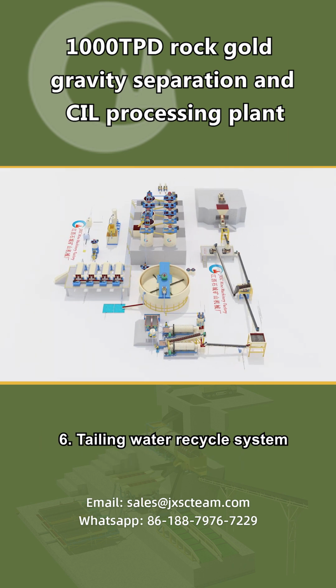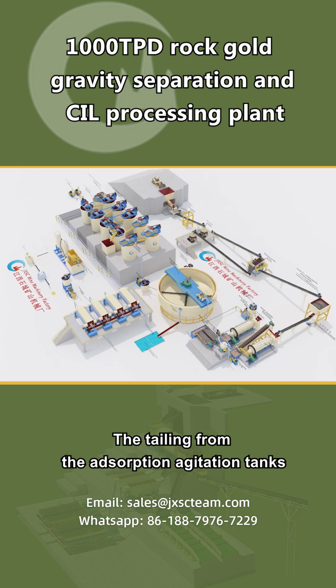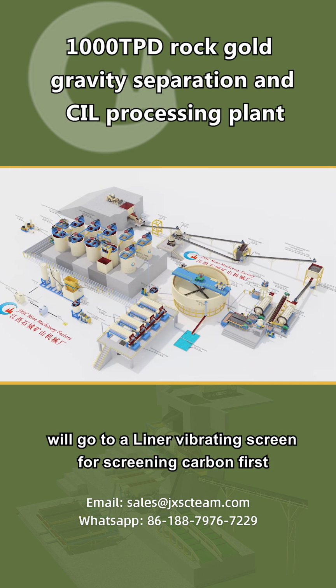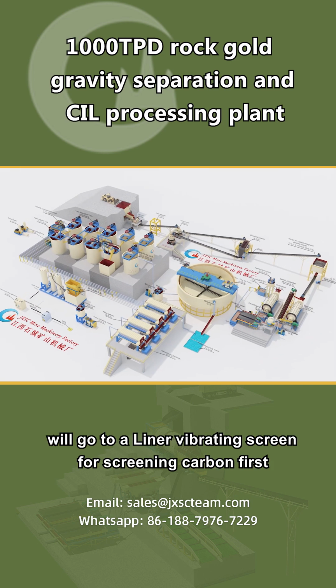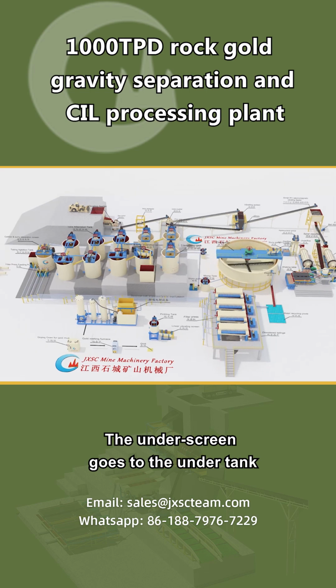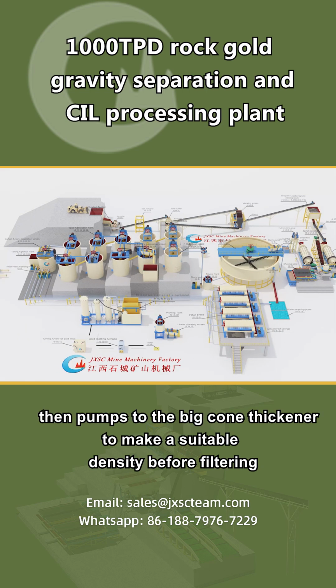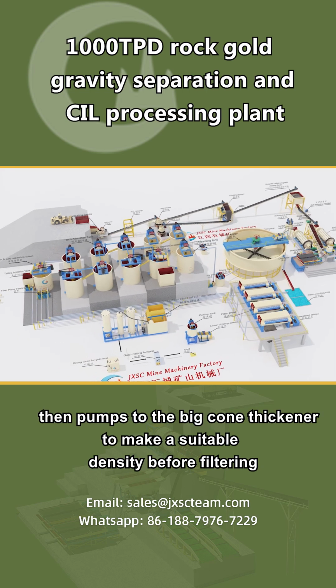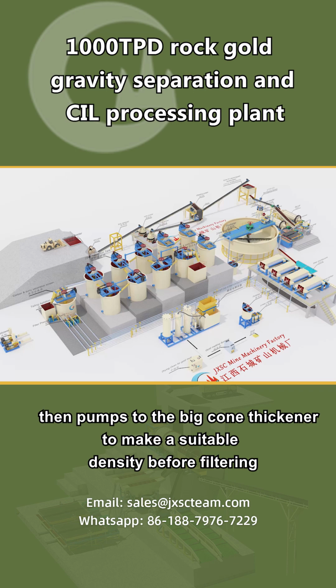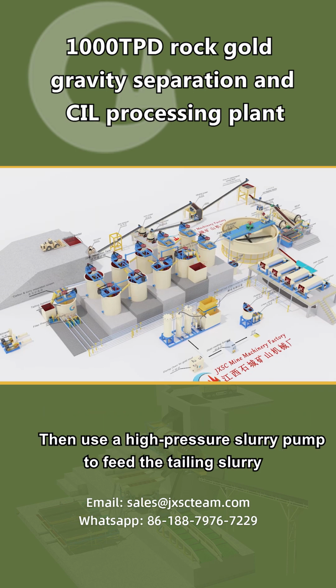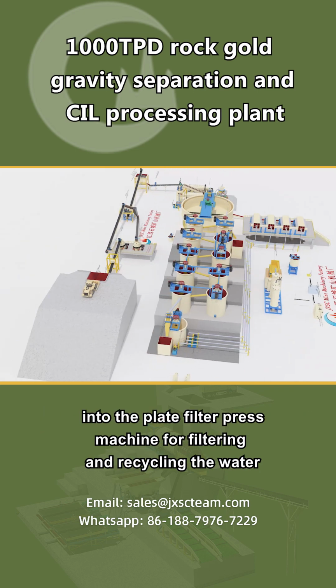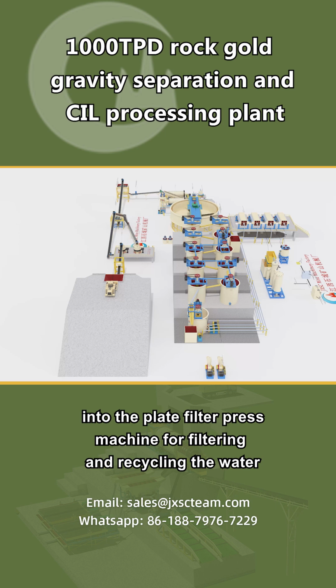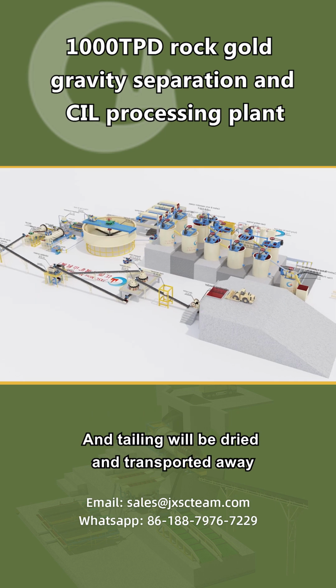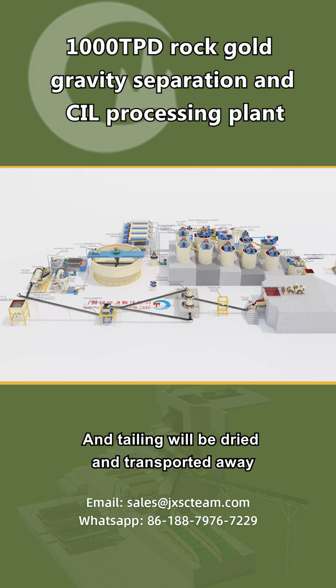6. Tailing water recycle system. The tailing from the adsorption agitation tanks will go to a linear vibrating screen for screening carbon first. The underscreen goes to the undertank, then pumps to the big cone thickener to make a suitable density before filtering. Then use a high-pressure slurry pump to feed the tailing slurry into the plate filter press machine for filtering and recycling the water, and tailing will be dried and transported away.